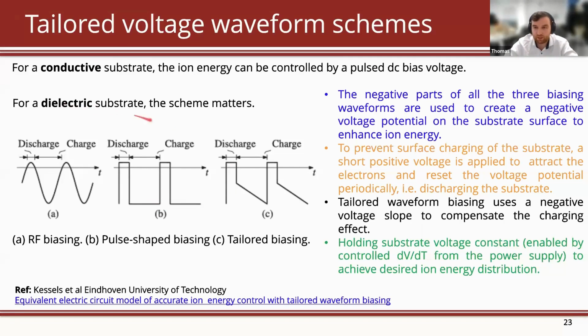If you're in a dielectric chamber, you have to change the shape a little bit. So what happens is as you pull positive charge down, you are charging up the wafer. So you'll have to compensate for the wafer charge building up for some amount of time. So this slope is helping compensate for that. And then you definitely have to do a discharge cycle where you pull in some electrons to discharge the wafer. And this does have to be tailored a little bit for different chambers and processes. Okay, so this is in general what you've got to do.